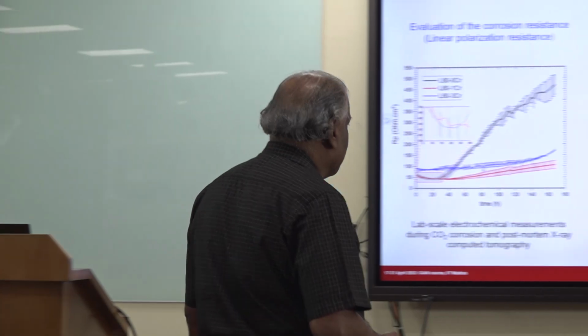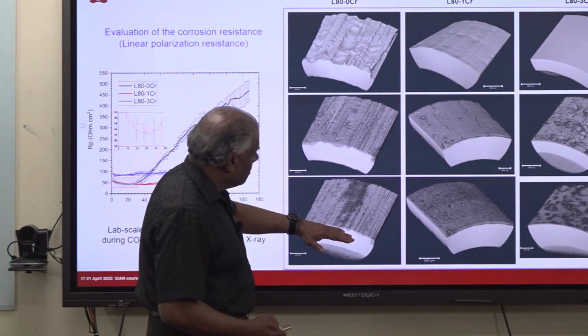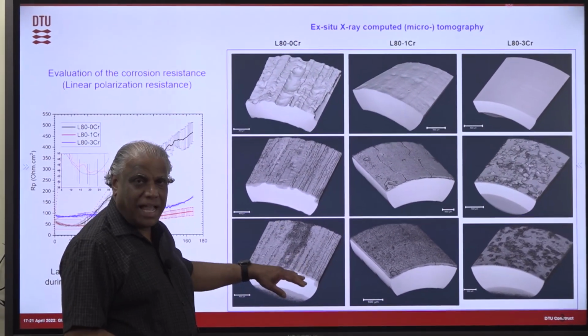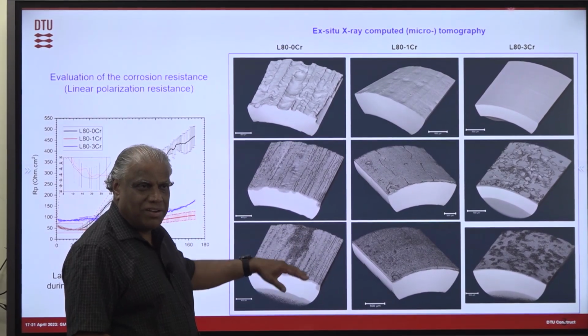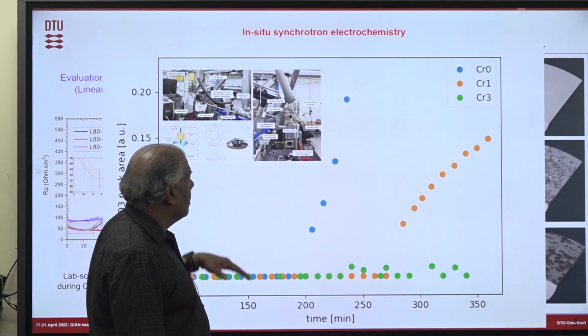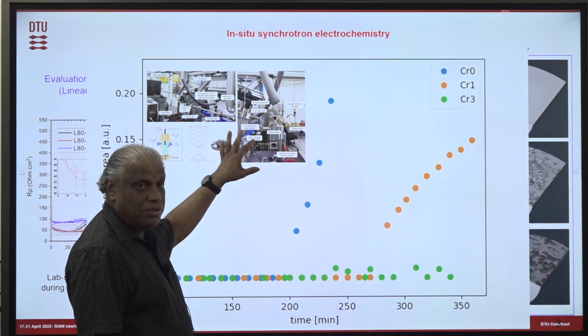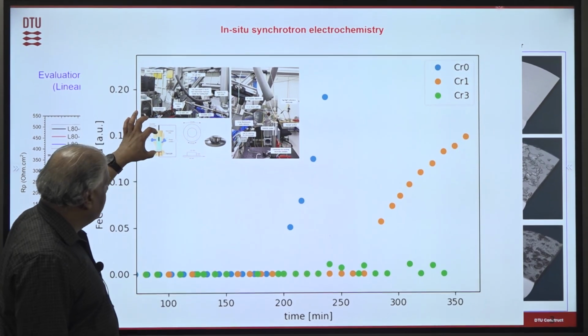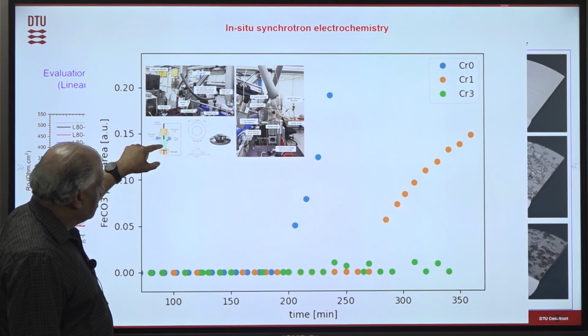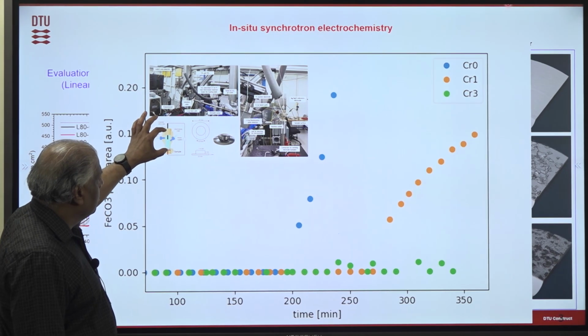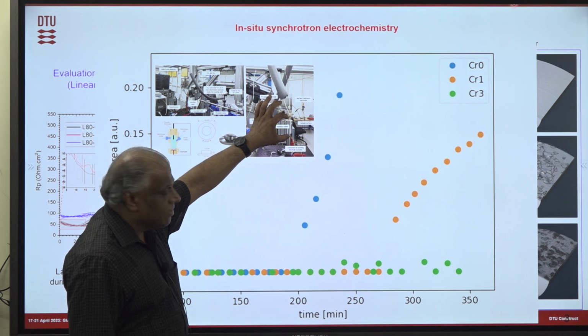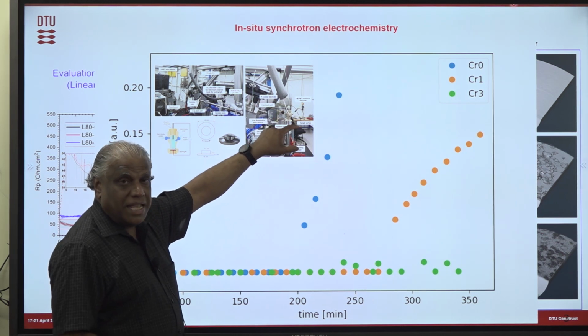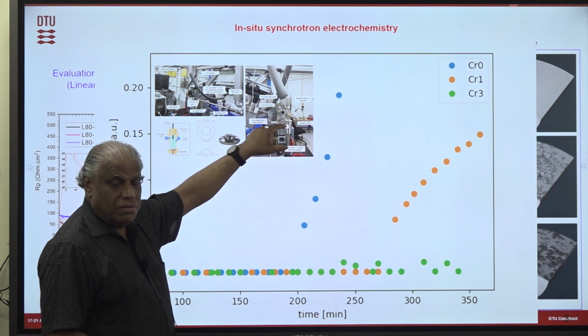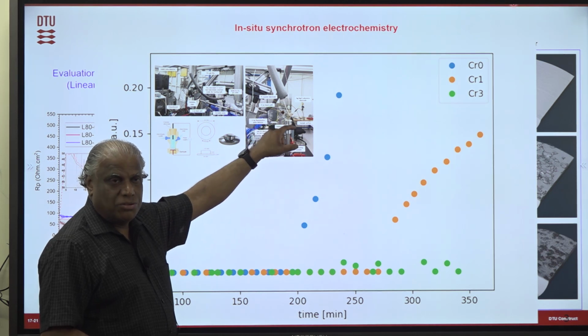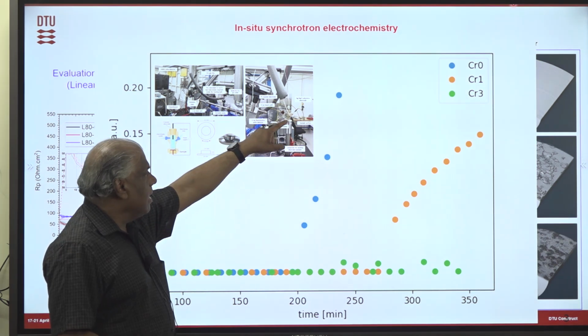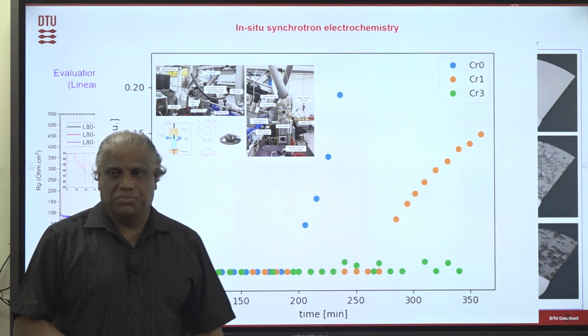Then we want to understand how this layer is building up, because when you analyze this layer, you will see iron oxide, iron carbonate, and different things. So we want to analyze that. That's the reason we use the in situ synchrotron, where we can have this kind of cell with the specimen, and put it inside the synchrotron. You have high energy X-rays in the synchrotron, so you can do the X-ray diffraction in situ and understand what kind of corrosion product is forming on the surface.